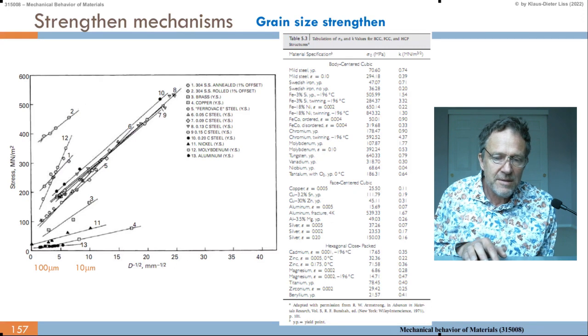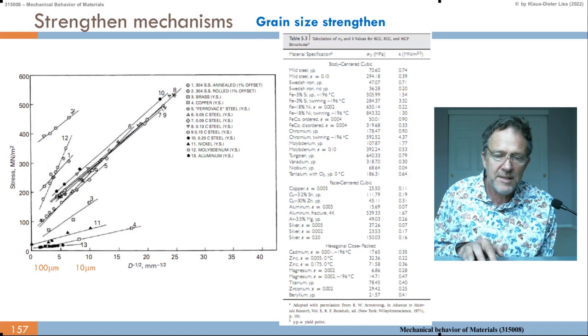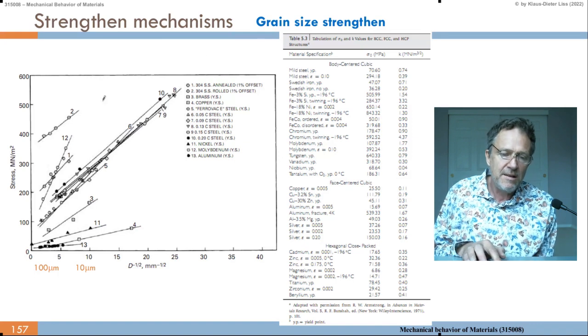2 is 304 stainless steel, which is rolled. So the annealed one has less stresses. But if we have a rolled steel, then it has work hardened already. So we have already dislocations in the material, and then we add further dislocations by our tensile testing, for example, and get this slope here.